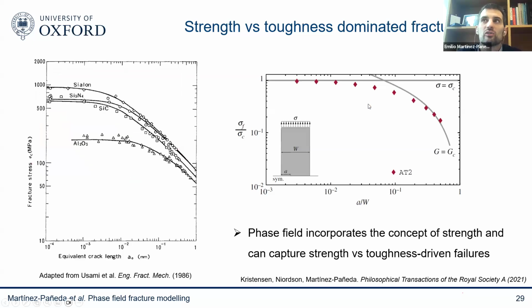And this is, of course, what we see also in experiments. These are experiments of fracture stress versus crack length on various materials. And you can see, of course, that we see exactly the same trend, and that therefore the phase field can handle any arbitrary length scales.